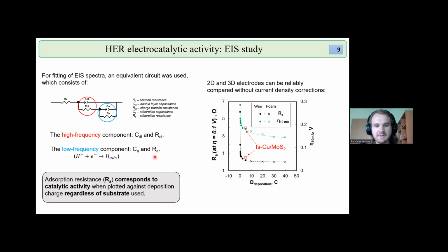But plotting these parameters here, as shown, the adsorption resistance measured at an overpotential of 0.1 volts, for molybdenum sulfide films that had been deposited on various substrates for a certain amount of charge, we notice a very clear exponential decay trend. So the circles here are molybdenum sulfide films that had been deposited on a wire electrode, and the X's are films that had been deposited on foam. We notice a very clear exponential decay curve of the parameter adsorption resistance against deposition charge.